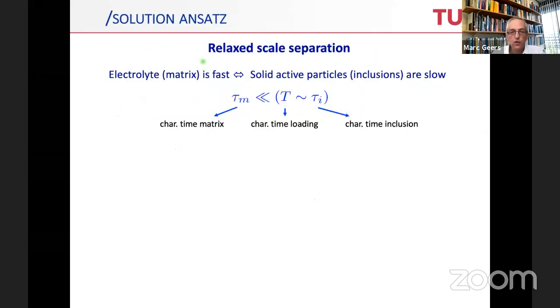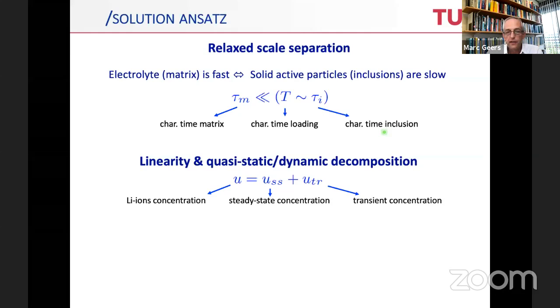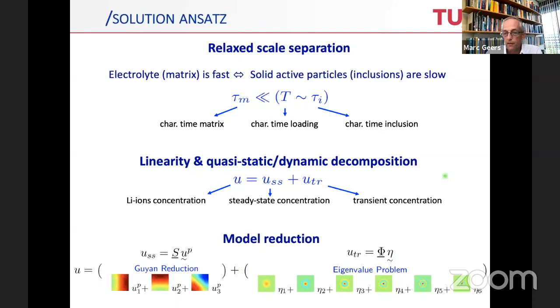Well, same machinery, so relaxed scale separation, what does it mean? The characteristic time of the matrix is much smaller than the characteristic time of the loading, which can be of equal order as the characteristic time of the inclusion. So again, inclusions are slow and the matrix is fast. A typical example is the battery problem, where the matrix role is played by the electrolyte and the solid active particles, which are slow, are the inclusions here. So again, linearity allows us to apply a quasi-static dynamic decomposition, where the dynamic is now in terms of mass diffusion, which allows us to split the concentrations into a steady state part and a transient part. And the transient part is then again treated by model reduction.